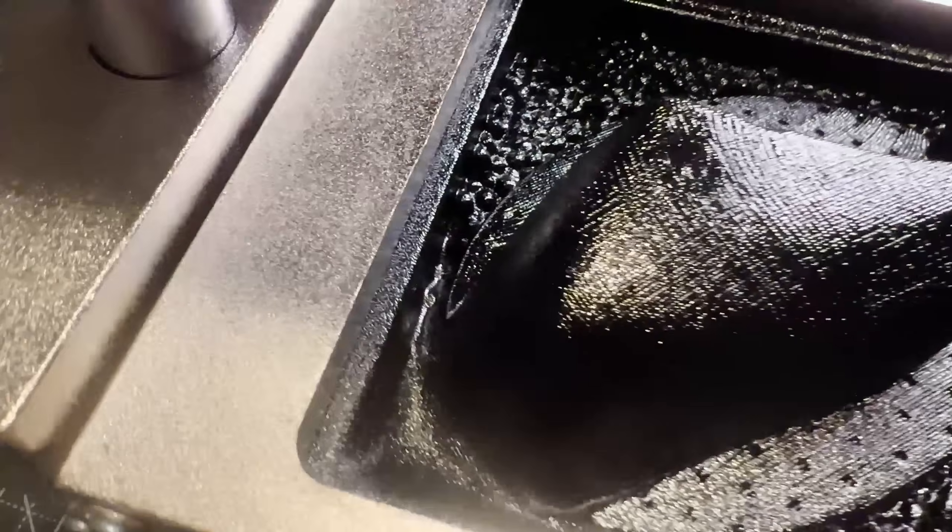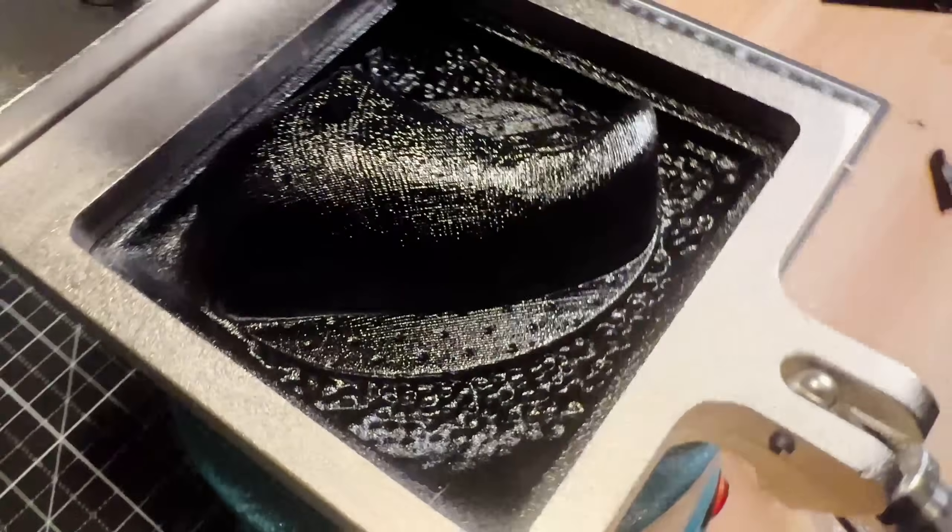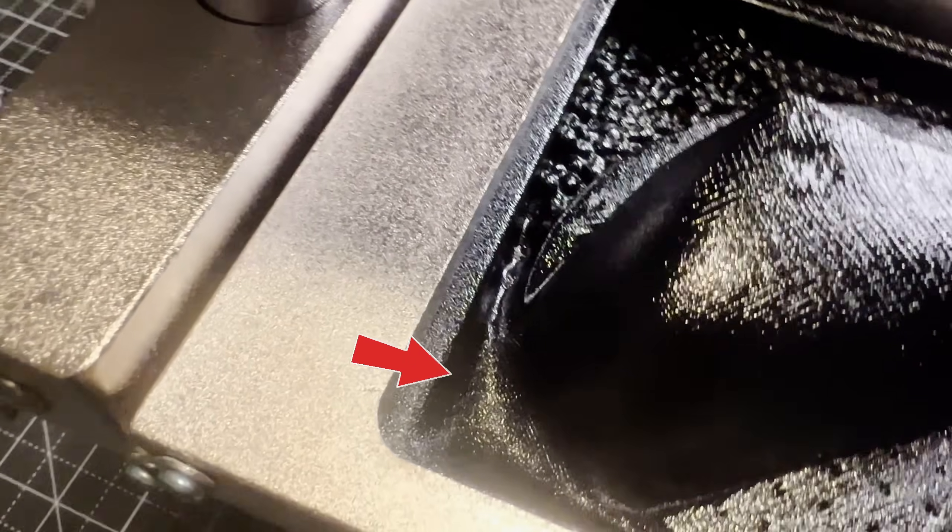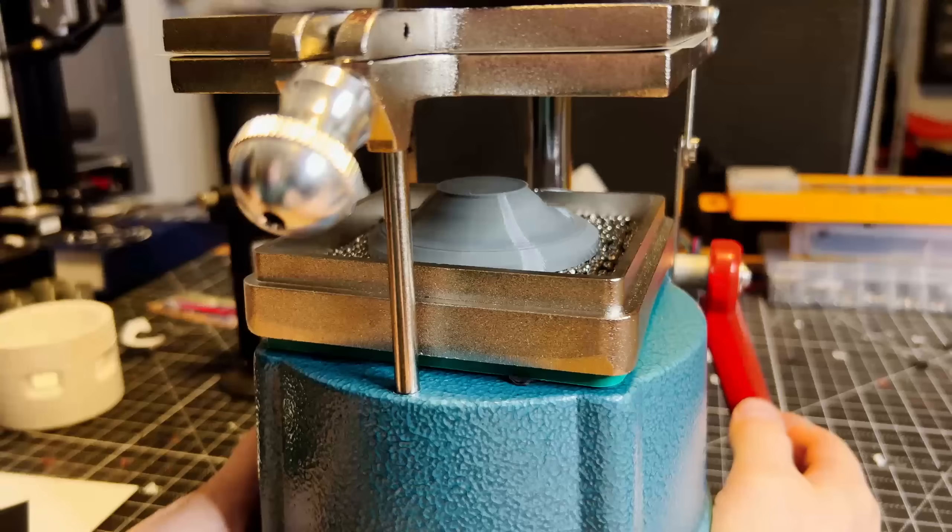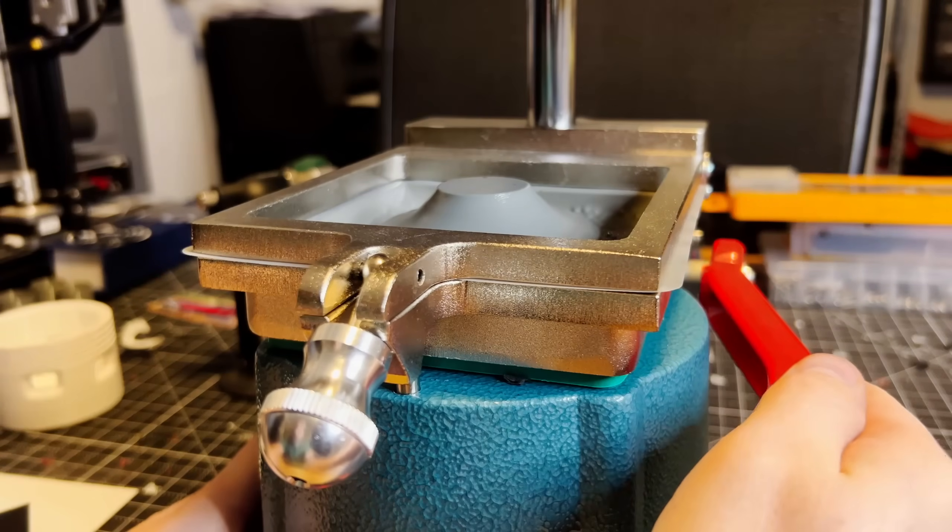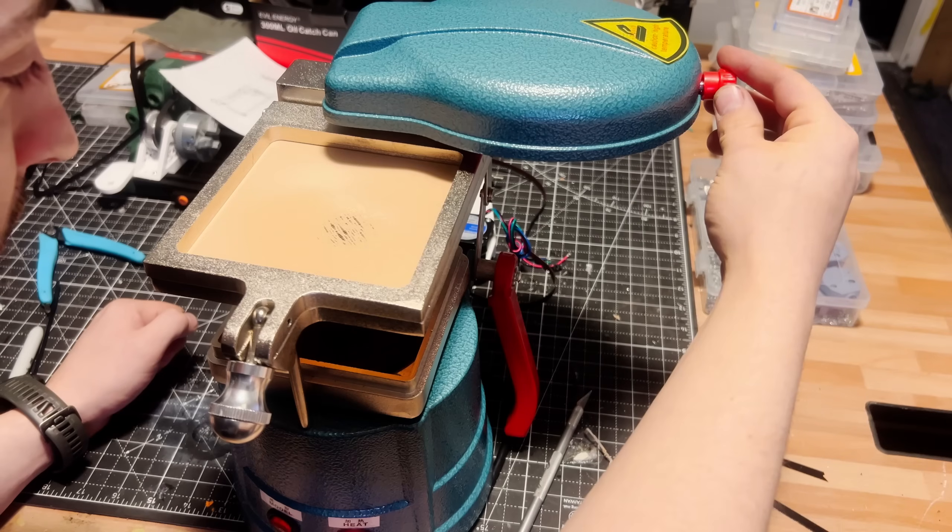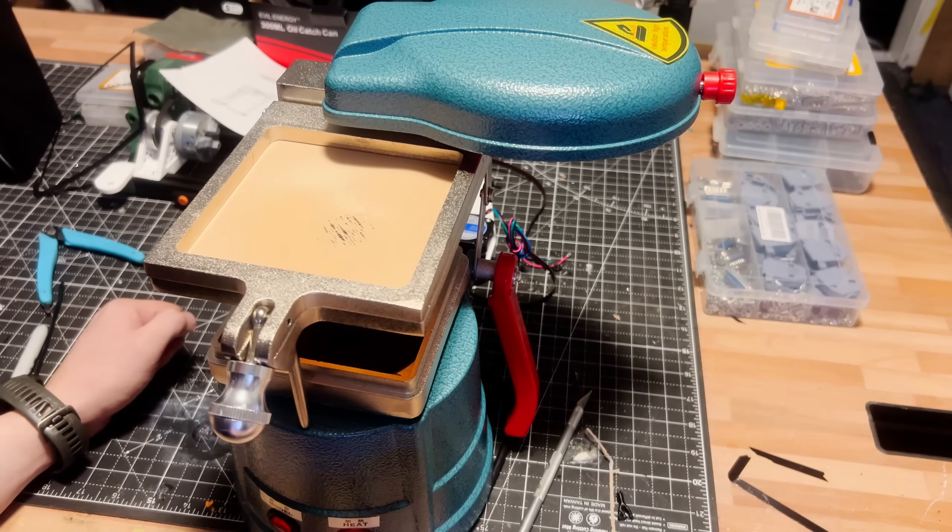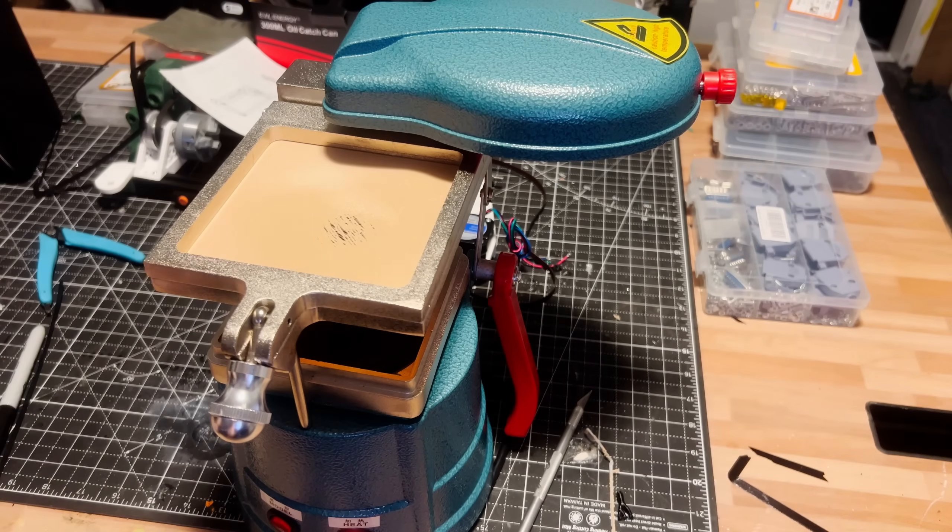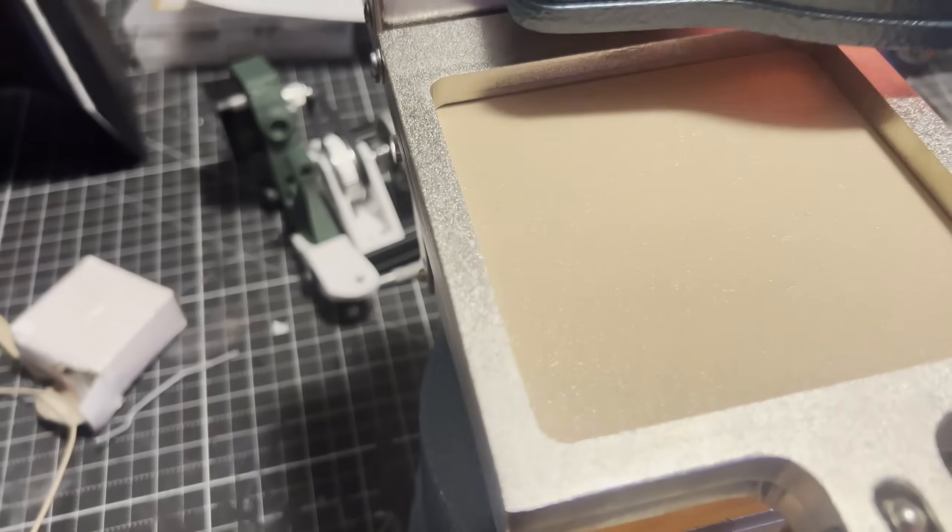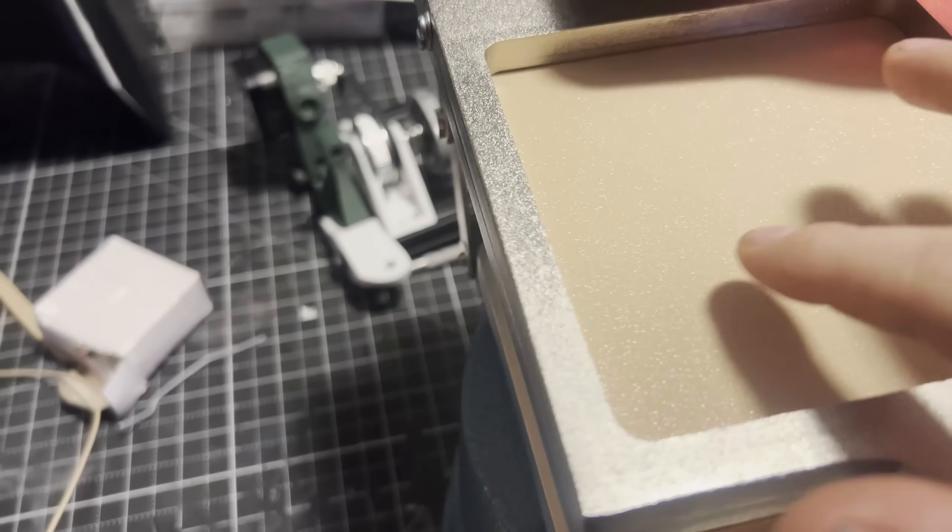Thirdly, thermoplastics are thermoplastics. I vacuum formed PLA, PETG, ABS, and ASA, as well as carbon fiber variants of a lot of them. The time it takes to heat them up varies, and with higher heat deflection temperature, the forming becomes less pliable at the edges where there isn't as much heat build up. I've had the most success with PETG, as PLA is very easy to overheat, and ABS and ASA are hard to tell when it's pliable enough, so I've ended up with quite a few duds from them.